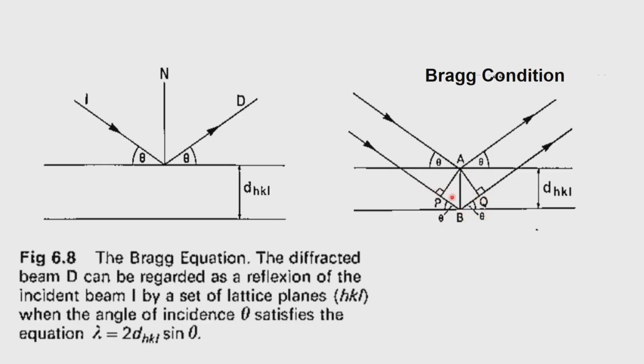The phase difference will now introduce what? It will tell us at what theta angle the scattering is occurring, and therefore the sin theta value can be calculated once we know the value of theta. If we know the sin theta value, then we can use 2 sin theta divided by lambda, which will give us the value of 1 over d_HKL. So, 1 over d_HKL will be 2 sin theta divided by lambda, and that is how we calculate this particular value. But I want you to do it as a home exercise.